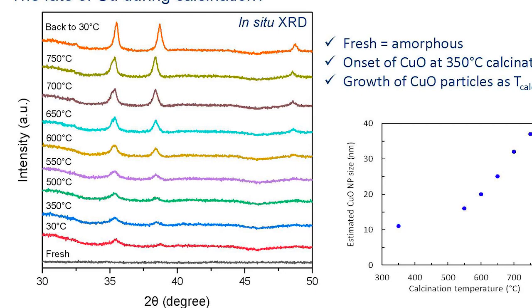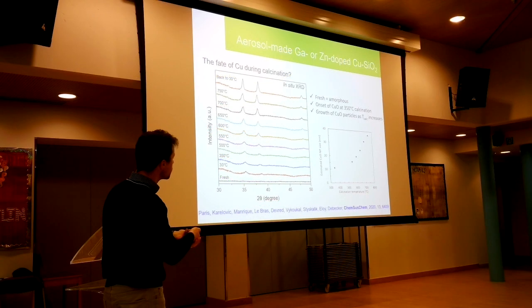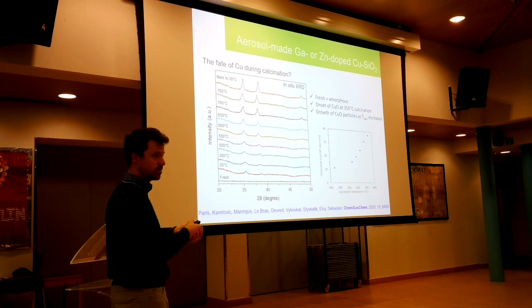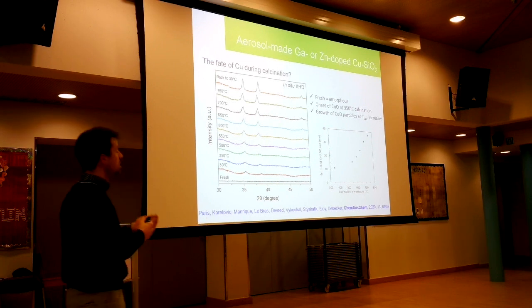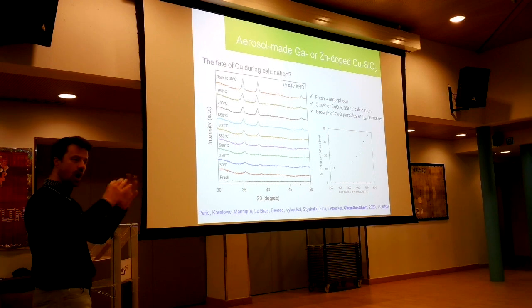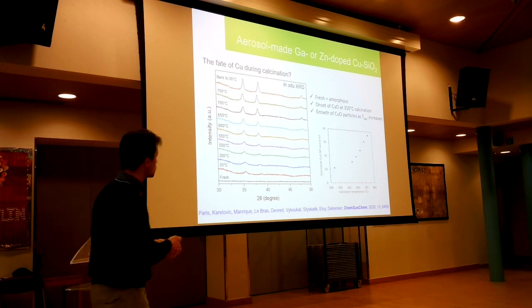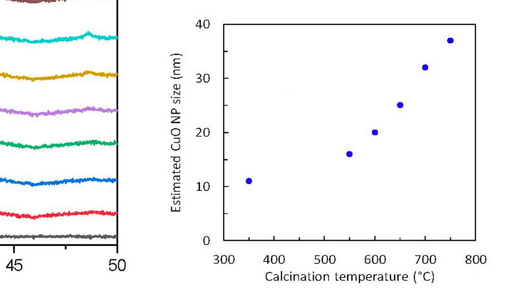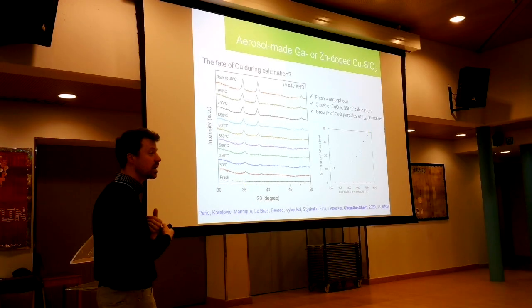From this peak, you can estimate the size of the copper oxide particles. And you can see that when you increase the calcination temperature, you increase the copper size. In catalysis, there's very often an optimum in terms of size. So that's a very precious plot for us. We can choose, depending on the size you want, you can just choose the calcination temperature and you're happy.